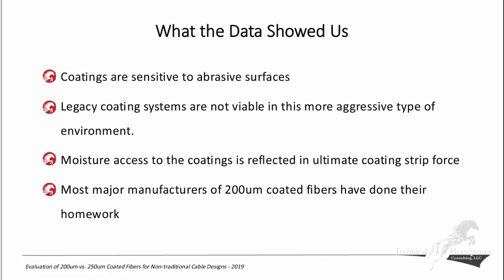Moisture access to the coatings is reflected in the ultimate coating strip force, so that's, I believe, a very viable test that we should continue to use, and it should become a much more popular tool in our toolbox. And the good news in this is that the major manufacturers we tested of the 200-micron coated fibers have really done their homework. Even though it's half the material, the performance is almost equal to the 250-micron fibers. So I give it to the fiber people who make the glass and the coatings. They have really done a fantastic job.